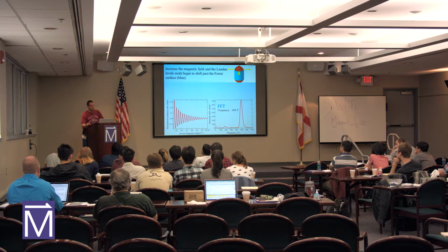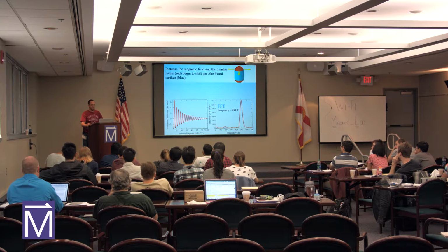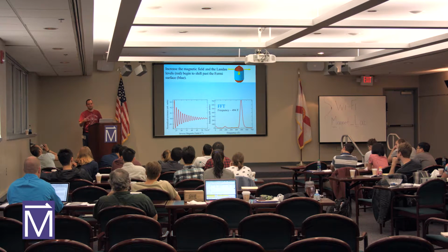For the most part, it's really a harder question recently, because if somebody has low frequency data, which is a big problem with all these Dirac fermion systems, they have low frequency oscillations. Majandel's nodding because he's had this exact problem. Normally we subtract a polynomial, but if you use a higher order polynomial and subtract that away from your data, then it can create oscillations, right?